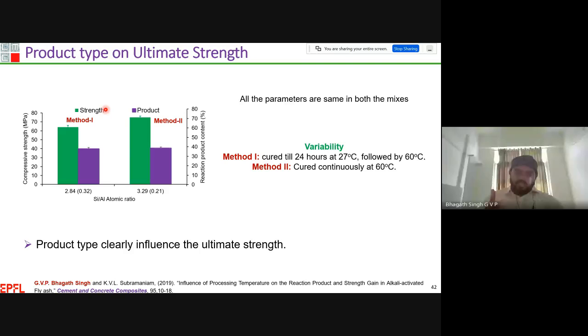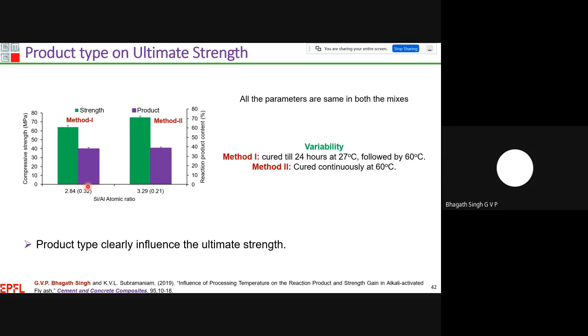If we compare method 1 and method 2, the mix proportions and everything is the same. The only variable is the curing condition. In method 1, cured for 24 hours at 27 degrees Celsius, followed by 60, I can see the silica to alumina atomic ratio is about 2.84. But the one I have cured continuously at 60, I can see about 3.29,